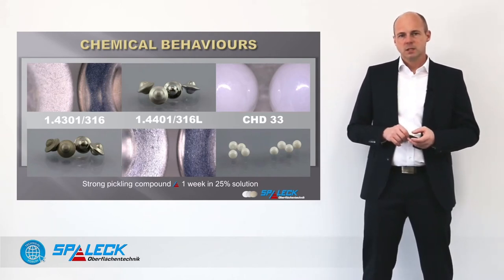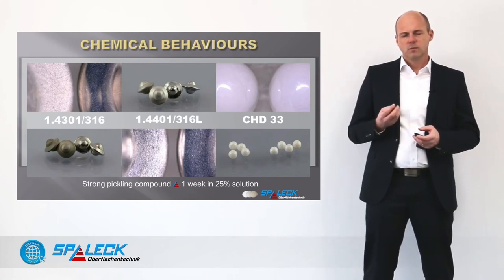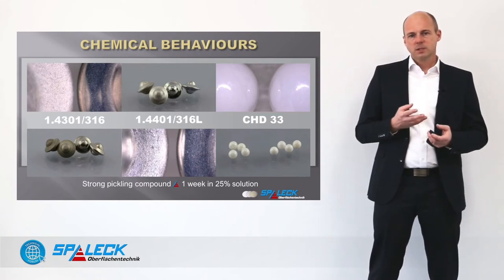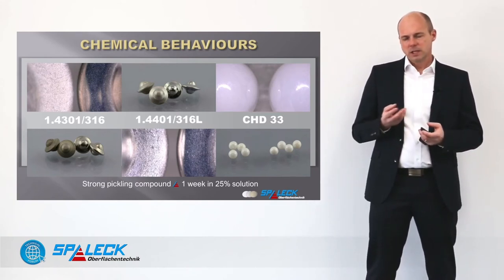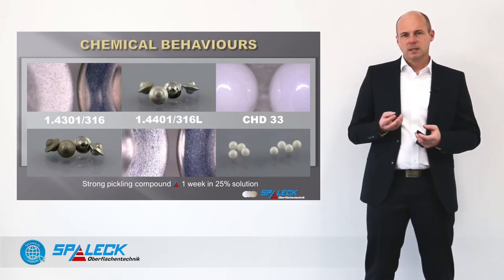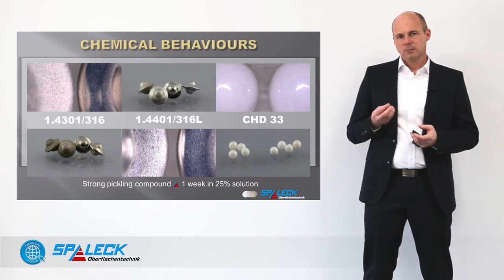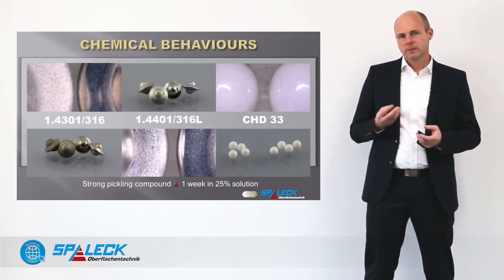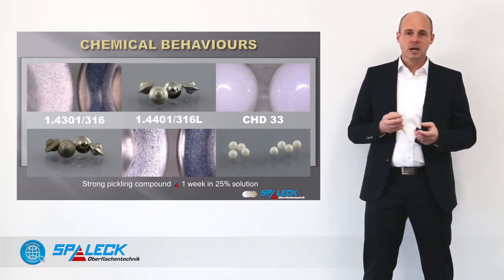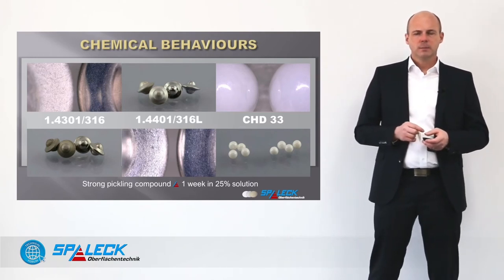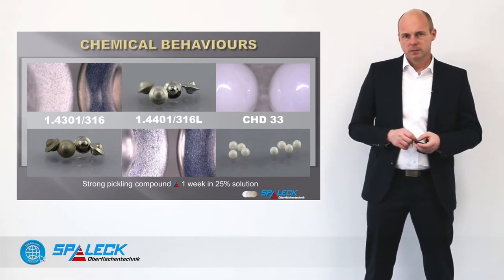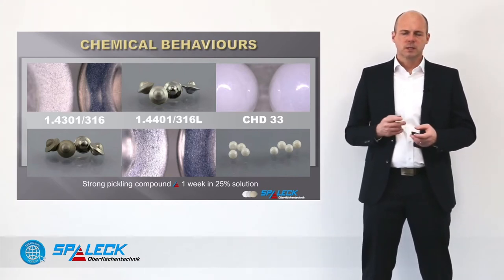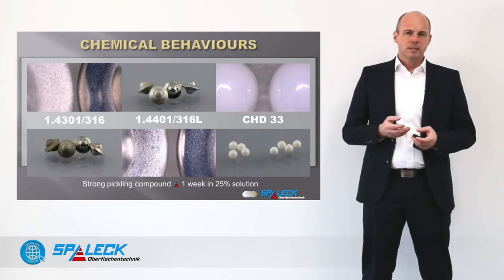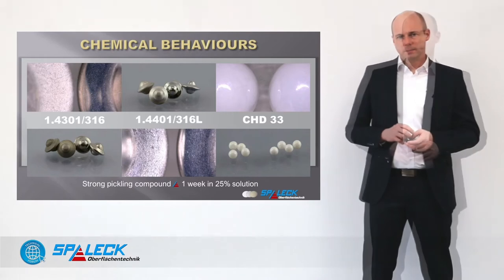But even there, you see that the strong pickling agent is having an effect on the surface, transforming the bright, shiny surface into a dull texture, and that reflects that particles, ions and metal have been dissolved from the surface of that material type. You can't see any evidence of chemical attack on the CHD media material, which is not a big surprise because from a chemical point of view, ceramics are in general very chemically inert. So, as a conclusion, I have to say Nele is right.